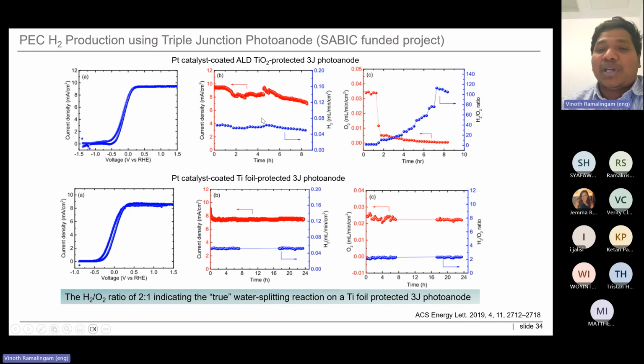Again, we did the same experiment. So we again got this stable hydrogen production as well as current density. But when we started measuring oxygen, up to 1 hour, the oxygen was stable, and then again it was lost. That means that even with the protection layer, it's not stable.